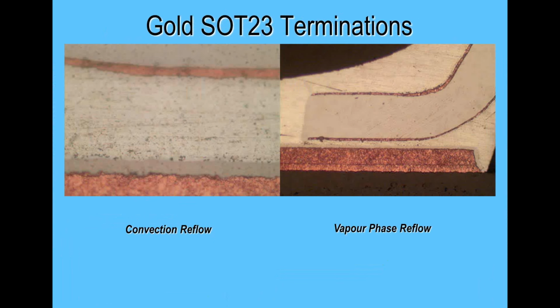And you can see on both these a close-up view and a slightly larger close-up view of the solder joint formed on the nickel, and then between the copper and the tin on the overplating on the lead termination. So here we've got probably a steel pin, and it's been copper overplated, copper flash, to aid wettability and solderability. So if perhaps you've got terminations which don't have an overplate and are not particularly solderable, that's where you start to have solderability and wettability problems.